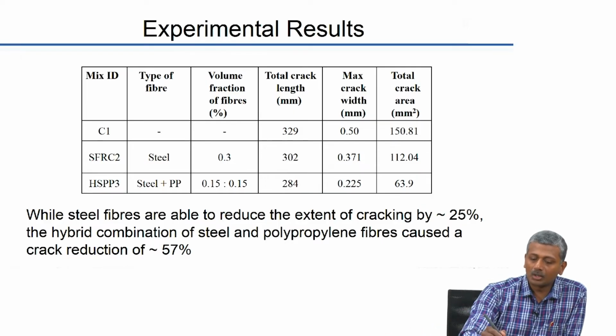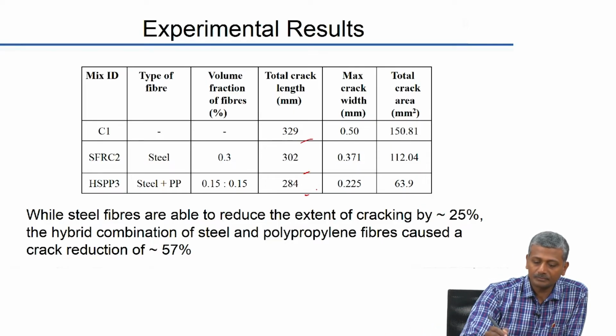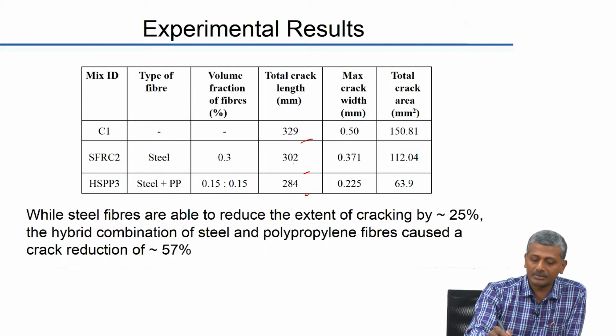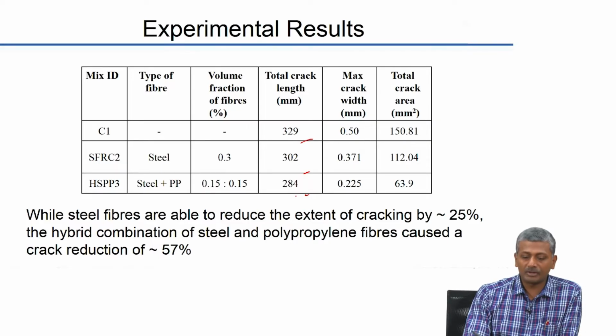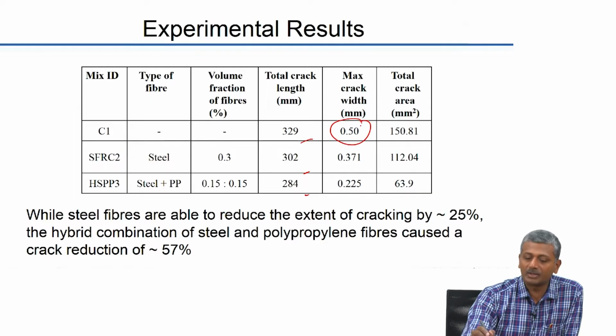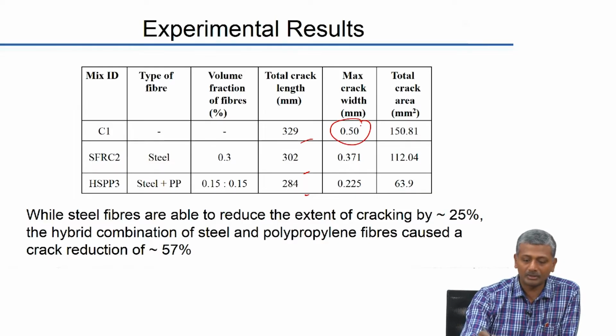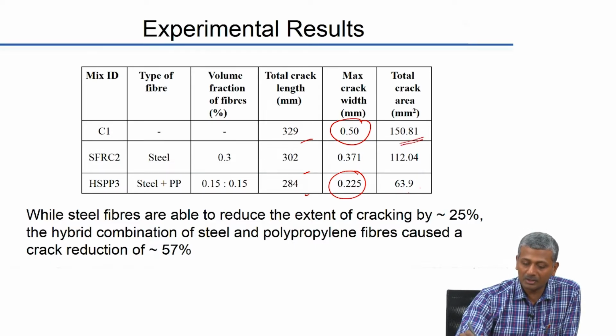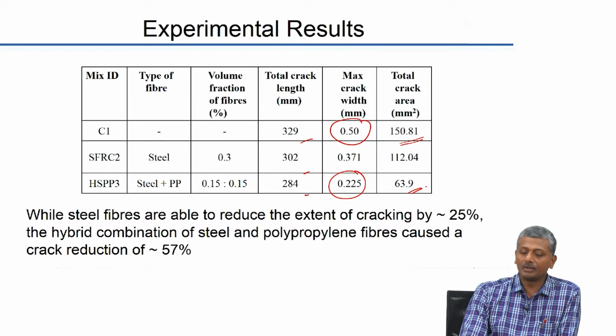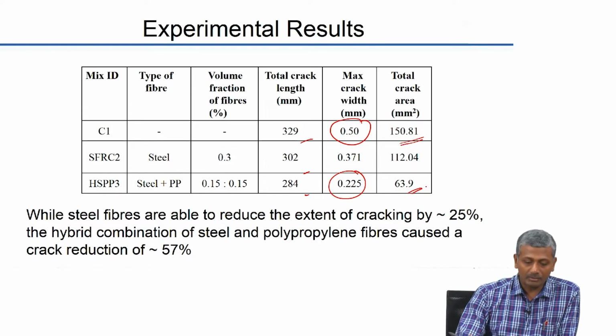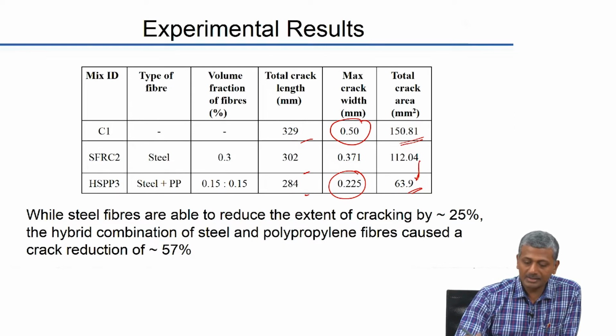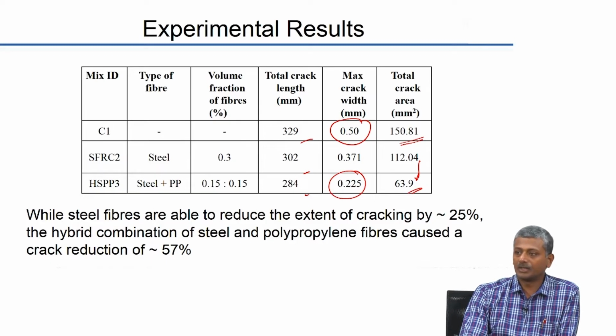And here this is describing the actual results. The total crack length is shown here, for the control concrete, the steel fiber concrete and the hybrid fiber reinforced concrete, and the maximum crack width decreased from 0.5 millimeter to 0.225 millimeter when hybrid fibers were used, and you can see the total crack area has been reduced significantly, okay. So, compared to even steel fiber concrete, the total crack area has come down by almost half, okay.